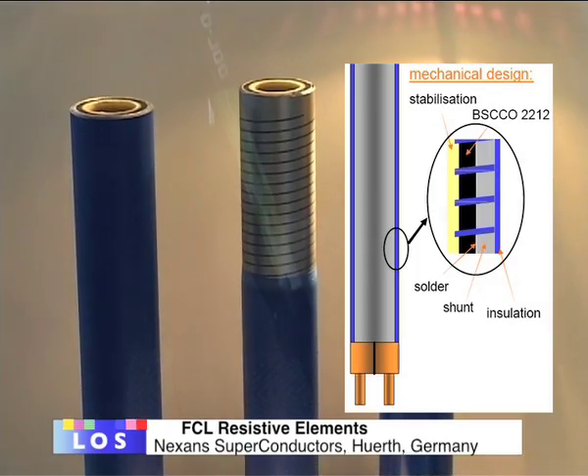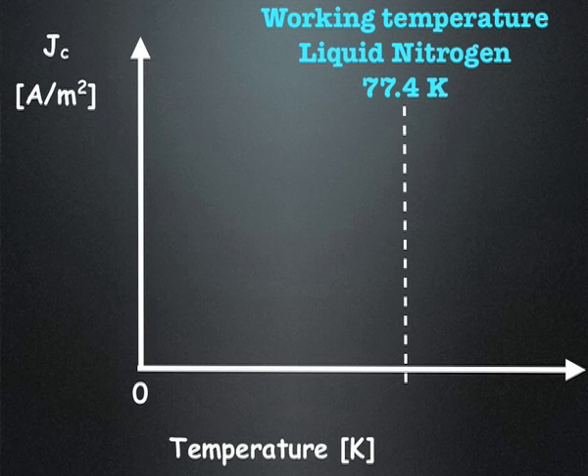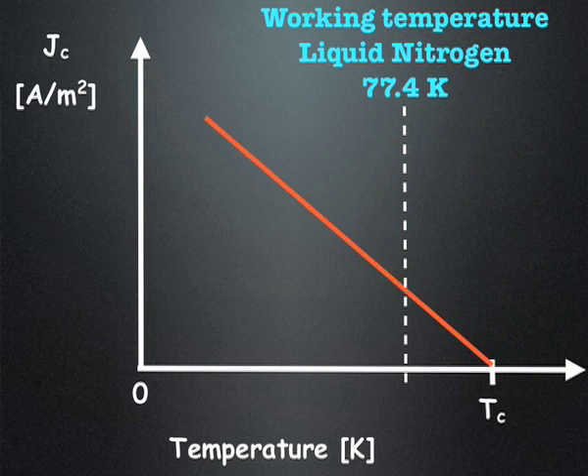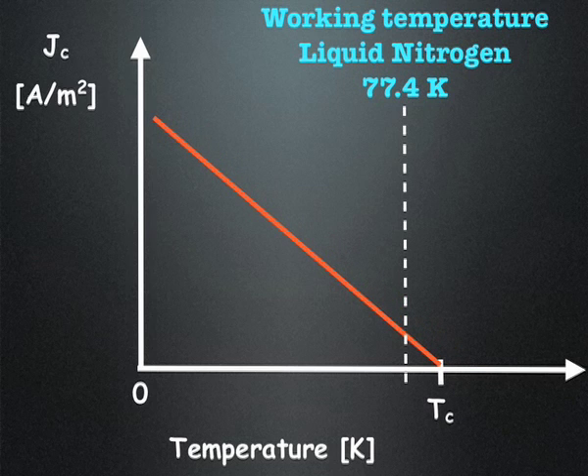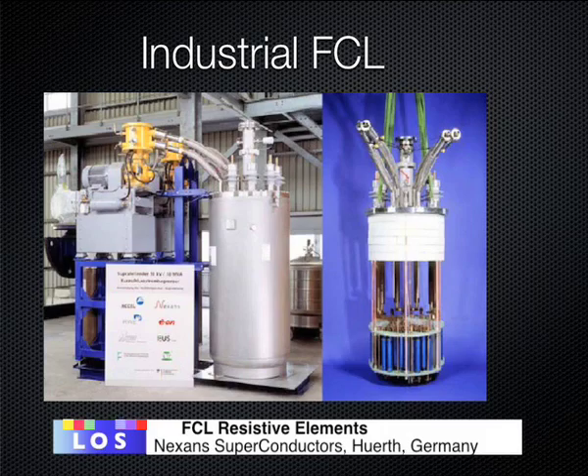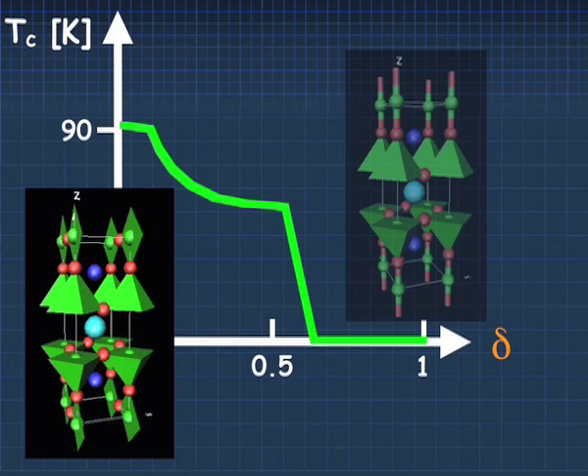For the recovery time, which is very important for a real application, the heat already deposited in the conductor must be removed as fast as possible. For the use of bulk material as a resistive fault current limiter, we realized we could reach better results if we decrease the temperature separation from the working temperature to the Tc. If you have a very big separation, you have very high current, but the inhomogeneities of your material can also be very big. It's very difficult when preparing a resistive fault current limiter to have a series of parts which are all homogeneous. Why not decrease the Tc by deoxygenating the sample?